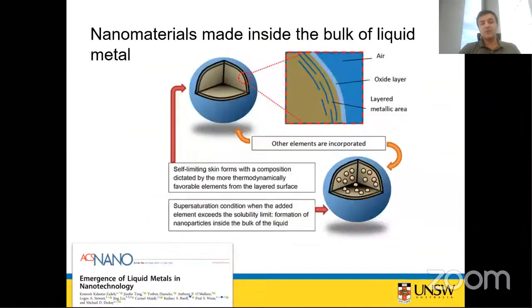We're talking about heterostructures. Look at this, this is a schematic of a liquid metal droplet. A liquid metal droplet, very interestingly, is a liquid metal, but the surface is layered. The gallium elements on the surface become very highly ordered. Tin elements on the surface become very highly ordered. And if it's exposed to ambient oxygen, it produces a very ordered oxide of that metal.